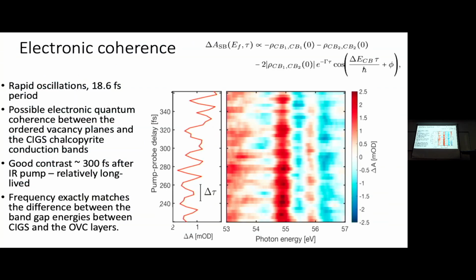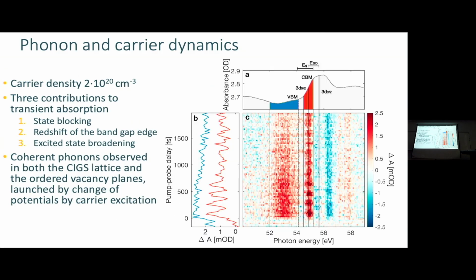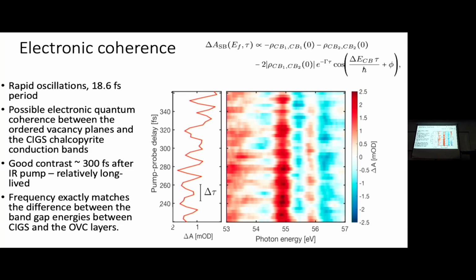Okay. Right. So now, because we know this has two different materials in it, we can look for other things, and we had a hint, like a glimmer of this, and then we tried to do a better measurement. If you go back to just one of these blobs of the coherent phonon and look at a much shorter time scale now, so you have to take points that are very closely spaced, you find there's another oscillation.